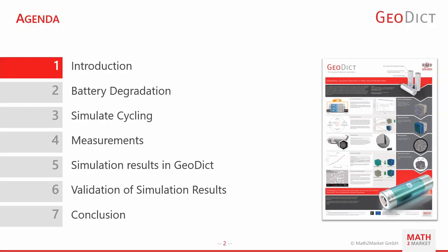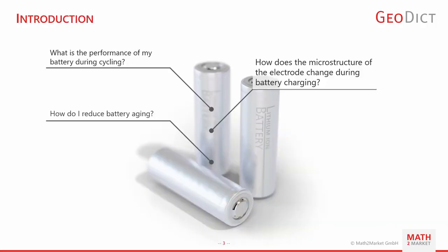In this project, we address the mechanical degradation of lithium-ion electrodes during charging using an experimental as well as a theoretical and simulative approach. The experimental approach is to analyze the microstructure of an NMC cathode and a graphite anode through 3D in operando X-ray tomography and through electrochemical characterization.